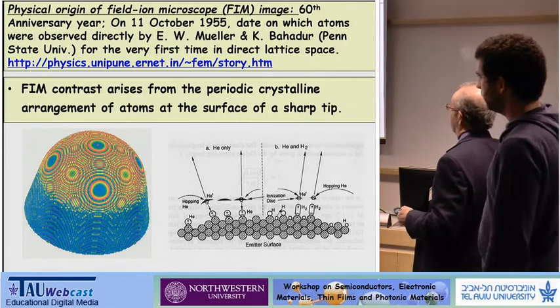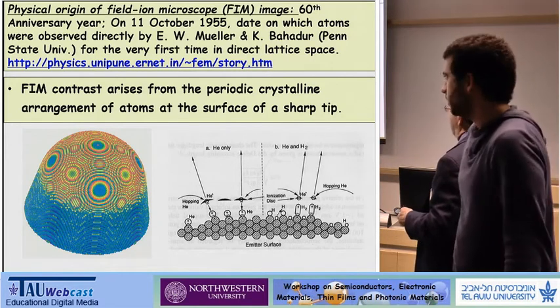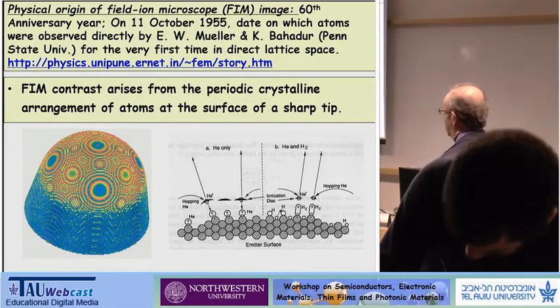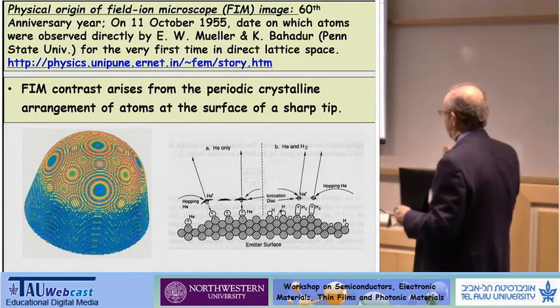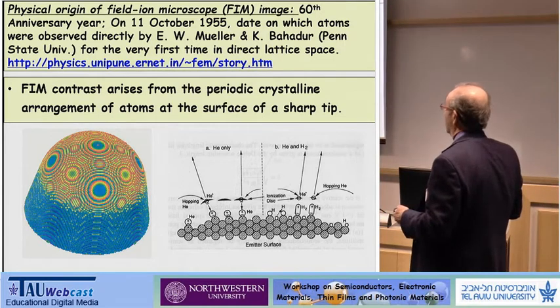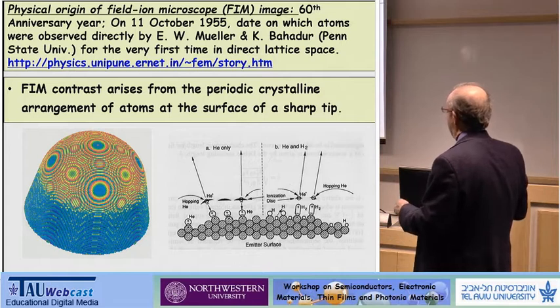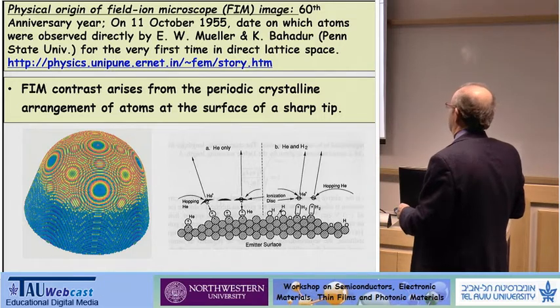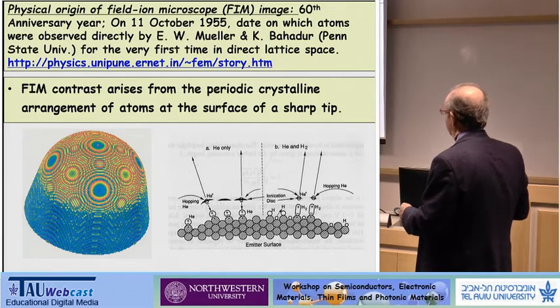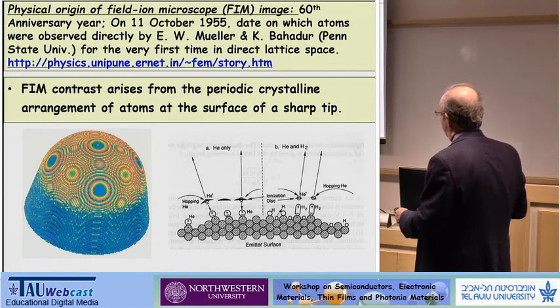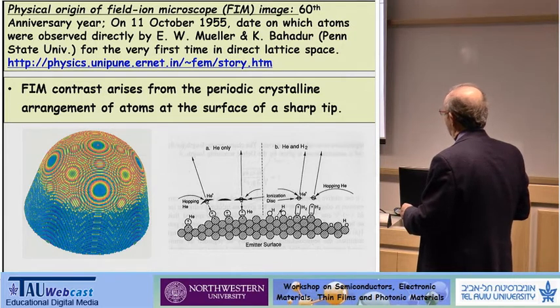Okay, so here is a simulation, as I said, and the atoms in red are the ones that you can see. And when you look at the atoms on a monitor, basically it's a stereographic projection to first order. And helium atoms are the messenger that tell you where the atoms are sitting. The helium atoms are highly polarized in the electric field, and they have a very high effective temperature. So when they hit the tip, they bounce several times on the tip to slow them down, to accommodate them to the surface temperature, which is around 30 Kelvin.